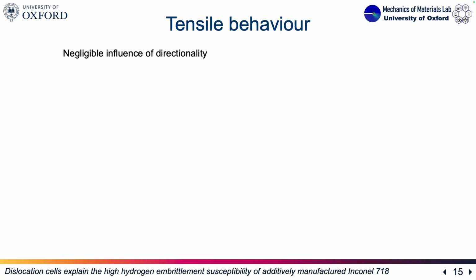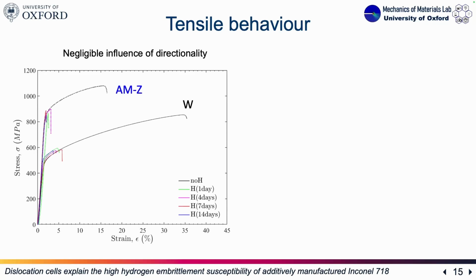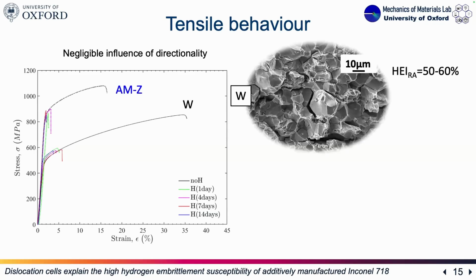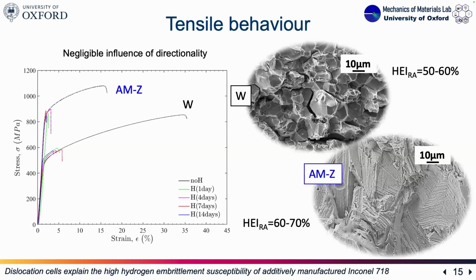Then we compare the tensile behavior. This is the part that Claudia did, so I'm just going to comment on it. We have performed tensile testing on, of course, uncharged and pre-charged samples for a duration of between 1 and 14 days, like we did for the TDS specimens. So you can see embrittlement is huge in both cases.